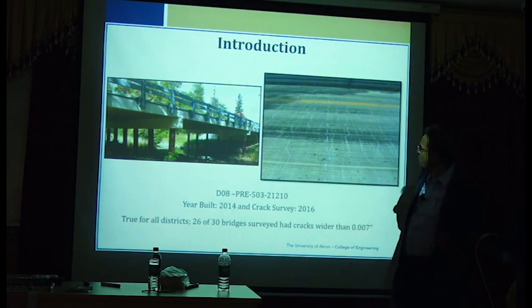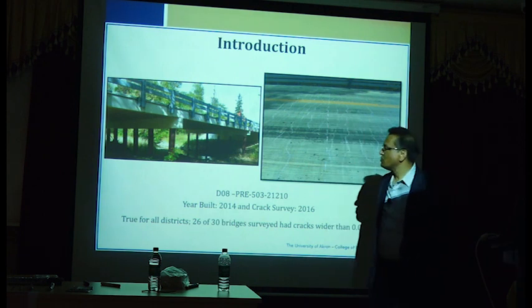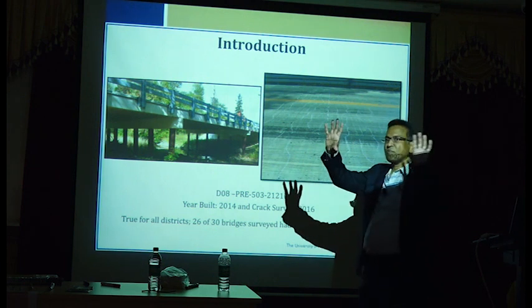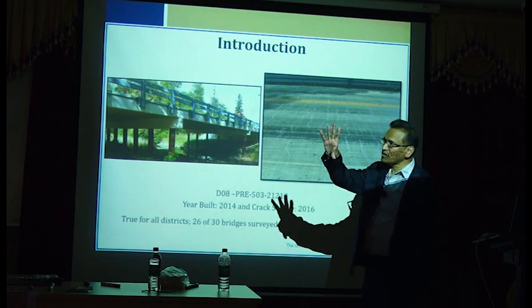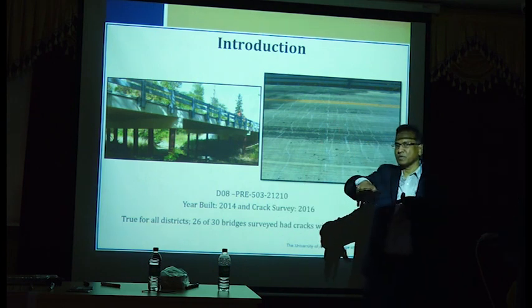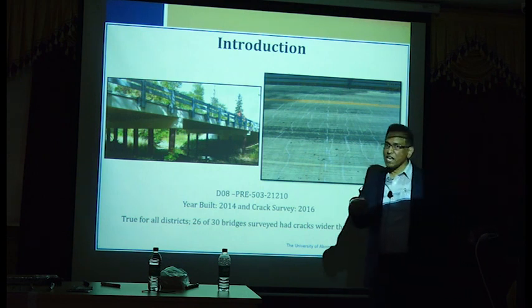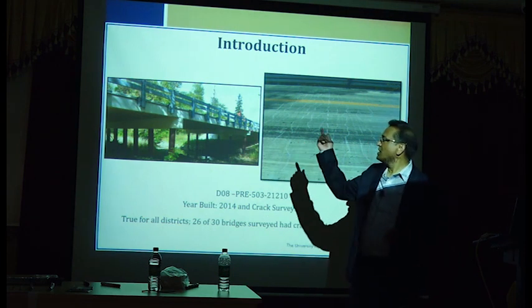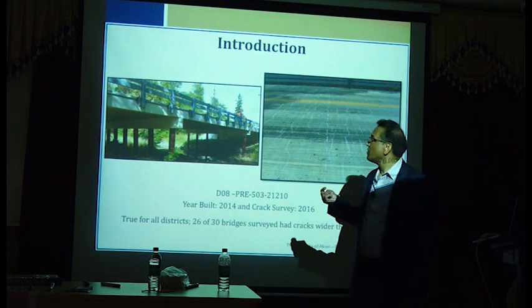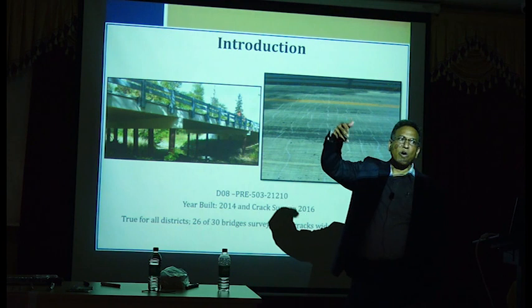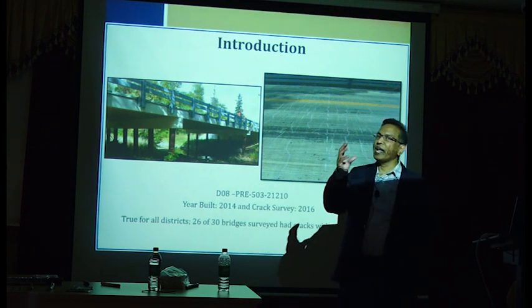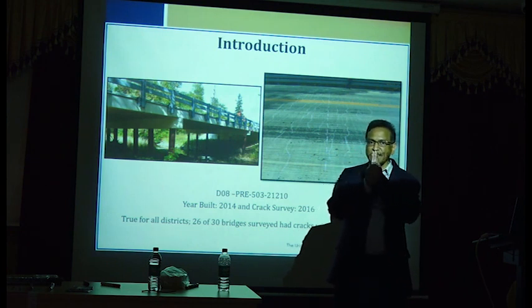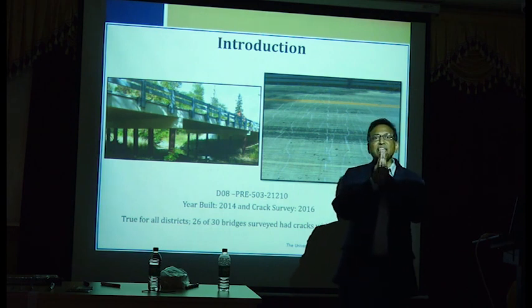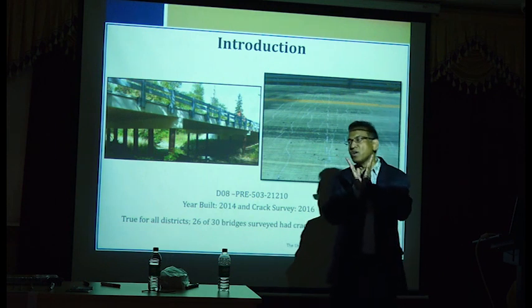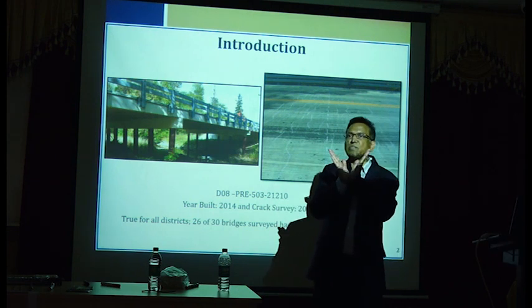But because of the continuity over the supports, you have lots and lots of cracks, hundreds of cracks and very wide cracks, because they're always optimizing the thickness. And if you optimize the thickness, you get a lot of cracking because you are making it more flexible. And then there is another problem. These bridges are in very cold areas. So anytime you have a crack, water penetrates the cracks, and then there is freezing. And when water freezes, it expands. That means it takes up more space, right? So the cracks are opening up. Every time there is freezing and thawing, it's becoming wider and wider. And then the dirt goes into the cracks, and it will permanently keep it open.